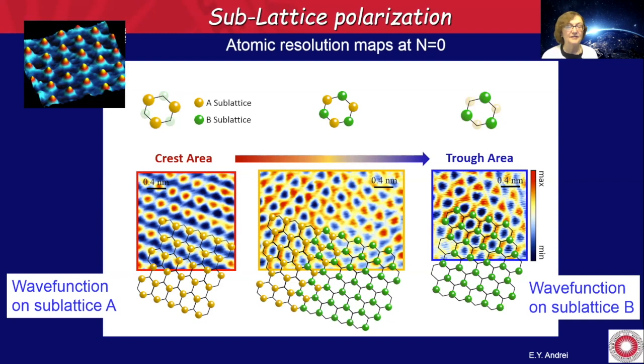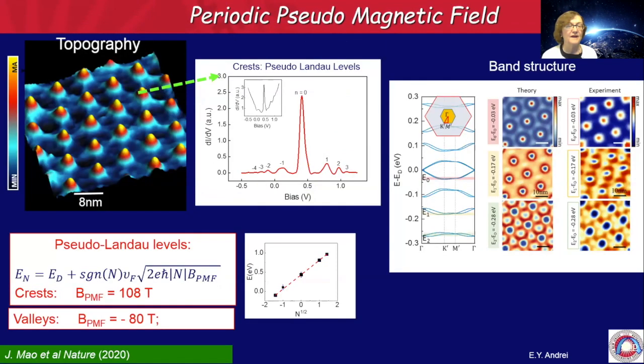So let's now look at the density of states and see if we have pseudo-Landau levels here. Here we look at the crest, and we take the dI/dV spectrum, density of states as a function of energy or bias voltage, and you see that you have pseudo-Landau levels forming. The first one is much higher than the others. Then you can plot the energy versus the square root of the Landau level index, and that gives you an effective pseudomagnetic field, which is humongous. It's about 108 Tesla. And then you measure the spectra in the trough regions, and you find that the pseudomagnetic field is about minus 80 Tesla in the troughs.